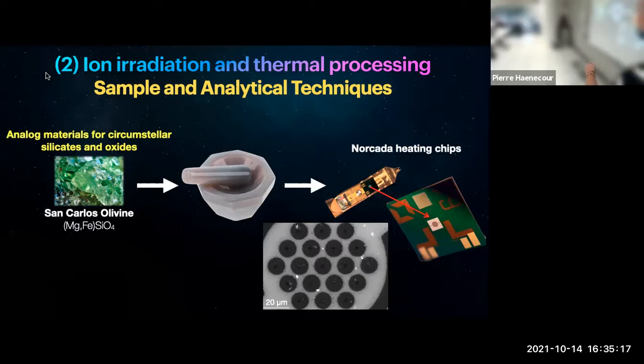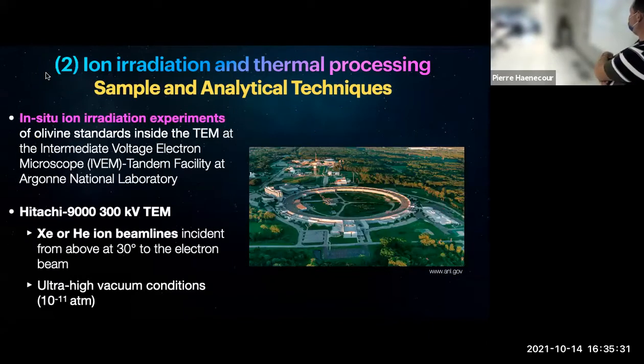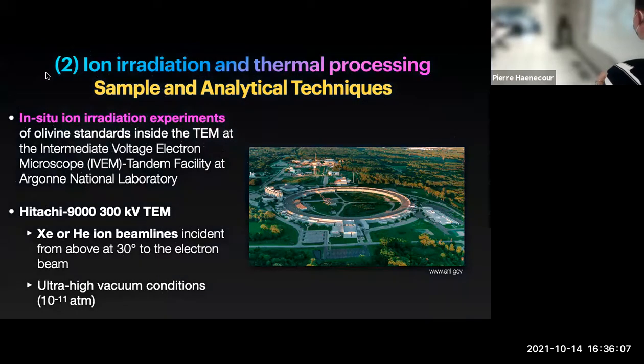We basically ground San Carlos olivine, then loaded it on the heating chips here, so it's small enough that it can be imaged in a TEM without any issue. Then we went to Argonne National Lab using the Hitachi 300 kV TEM that's connected to a xenon and helium ion beamline, so you can irradiate your sample with either xenon or helium. This line is at a 30 degree angle going through the electron column. So you can image your sample as it's being irradiated by xenon or helium ions, and it's in extremely high vacuum.